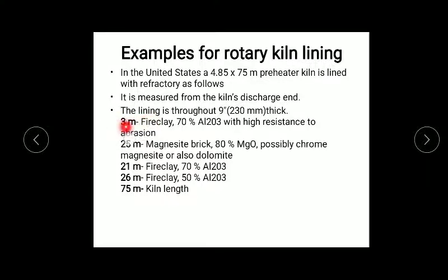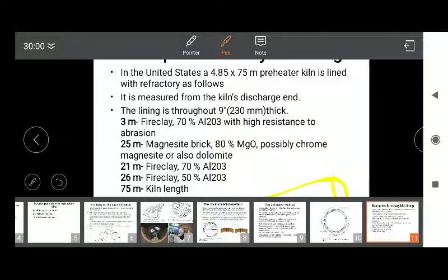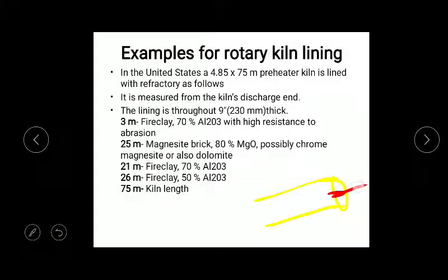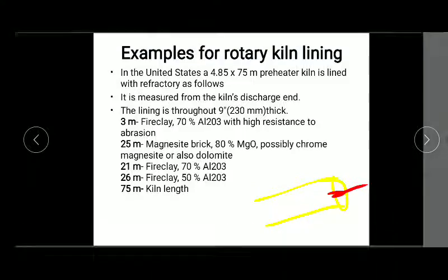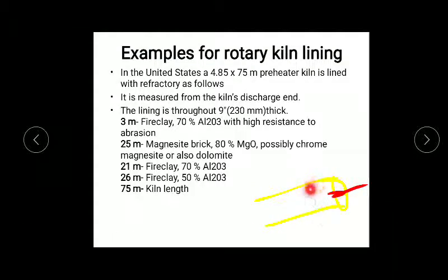From the discharge zone, the 3 meters is, suppose, this is your rotary kiln, and this is your burner here. This part near the burner, 3 meters, is fire clay with 70% alumina with high resistance to abrasion. Then the next 25 meters is magnesite brick with 80% MgO, possibly chrome magnesite or also dolomite. So the next 25 meters is this.